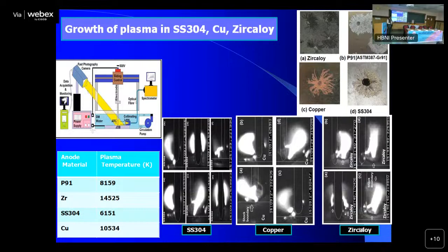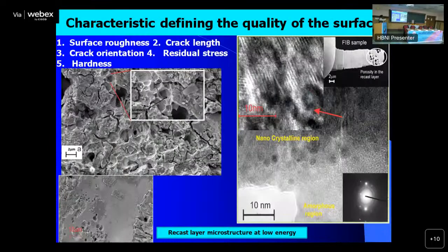So what is happening is not only craters are forming, the microstructure of the top layers is getting completely changed. Because of this melting and solidification, you have completely new microstructure on the top, and therefore the properties will be very different from the base material. That is another area of concern. So you have surface roughness, you have cracks, lengths of those are important, crack orientation, residual stress, and of course hardness. So this is one such cut surface of P91 made by high energy. We have seen this surface on the plan view to get an idea about the nature of the crater, the size and so on. We have also examined the cross section to see how deep is this effect.